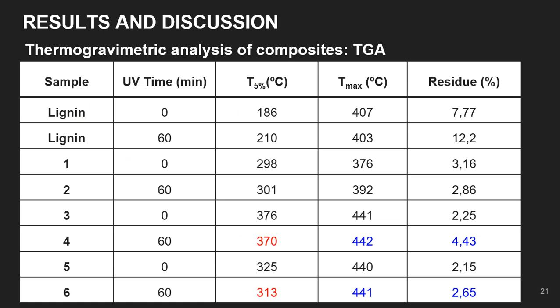In the present table, it is possible to observe more closely the values of the phenomena just mentioned, where it can also be observed that the residual rate at the end of the analysis increases for the samples with photochemical treatment. This is indicative of the formation of char resistant to high temperatures.